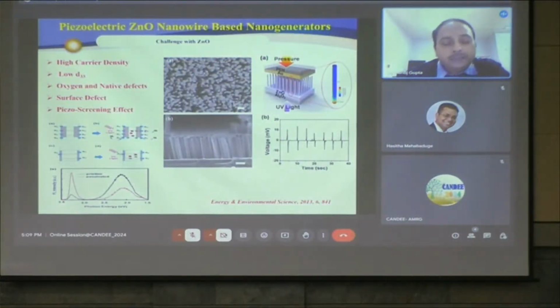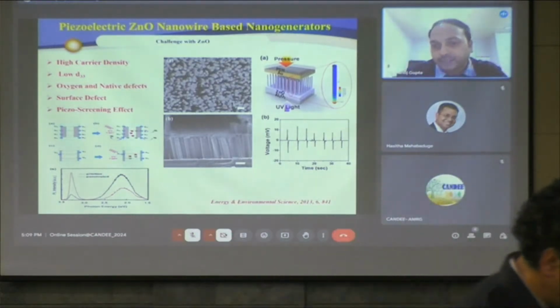Now there are many native defects within the zinc oxide nanowire. Like if you shine UV light, what will happen? A lot of electron and hole pairs will be generated, and these electron and hole pairs will screen the piezoelectric potential. So we also passivated these native defects by thermal annealing, so that we can get a constant output voltage even under UV light. This is the harsh condition.